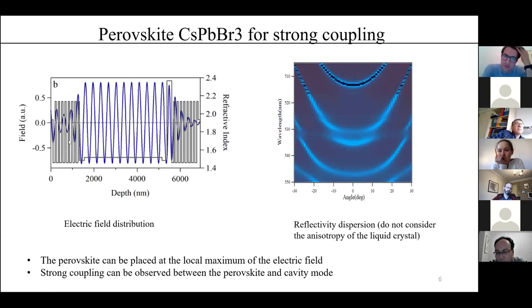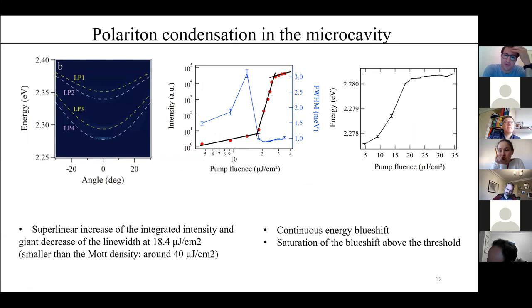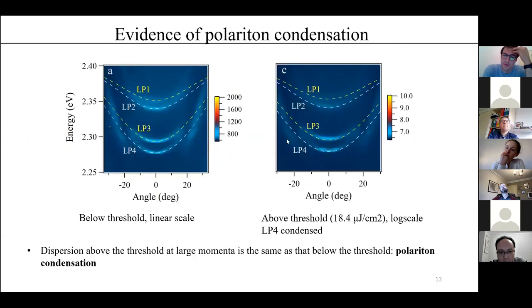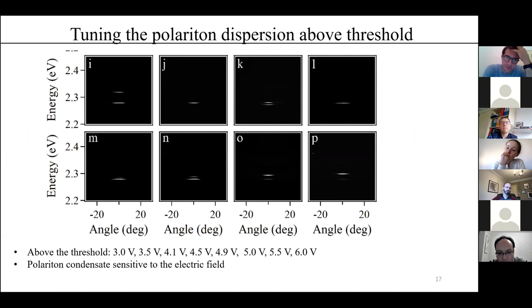And also there is a nice experiment which you did when you play with the voltage, and you show that you can tune the polariton lasing wavelength nicely in your system. I'm wondering if you see any difference in the threshold when you tune it. Yes, I see. What's the difference? Where do you see the maximum and the minimum of the threshold? The minimum threshold, I believe, is around, sorry, I will check with my students. It's not changed too much. But sometimes, for example in this experiment, we see that when the voltage is larger than 4.5 volts, the threshold seems to be increased. Sometimes we cannot see condensation or lasing of polaritons when the voltage is larger.